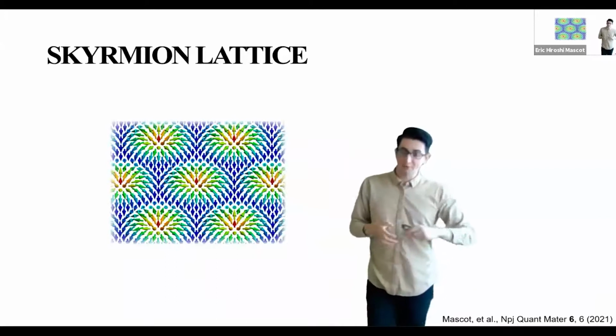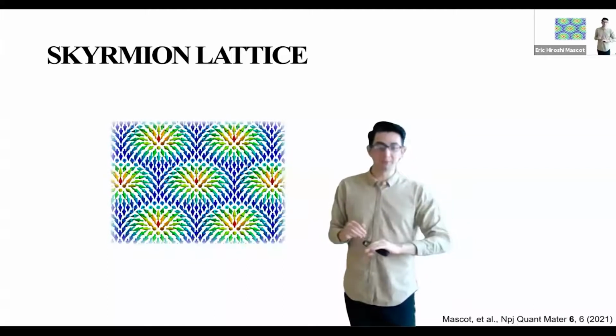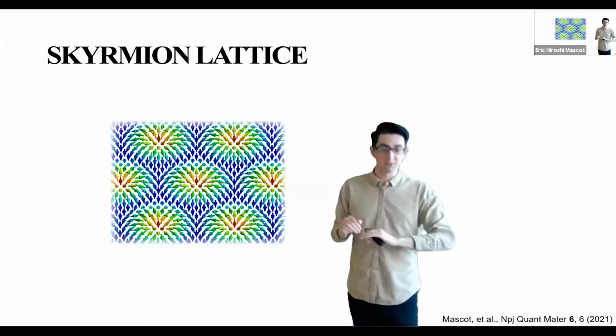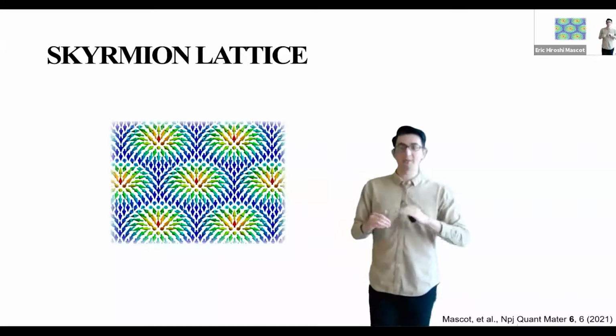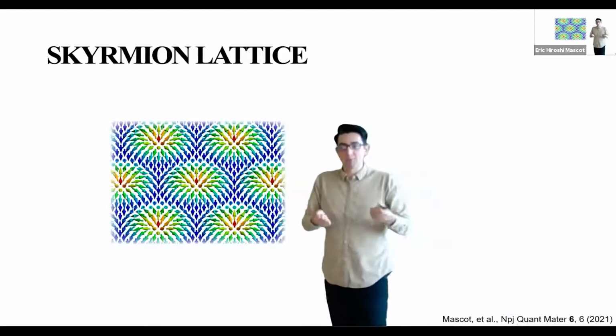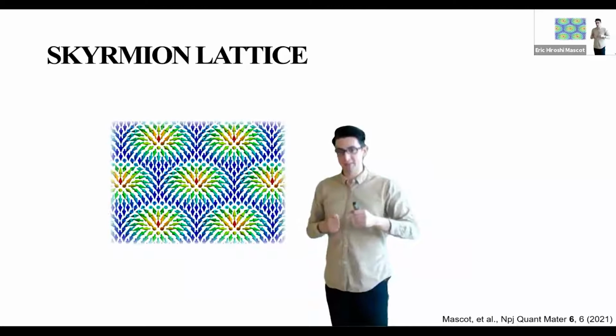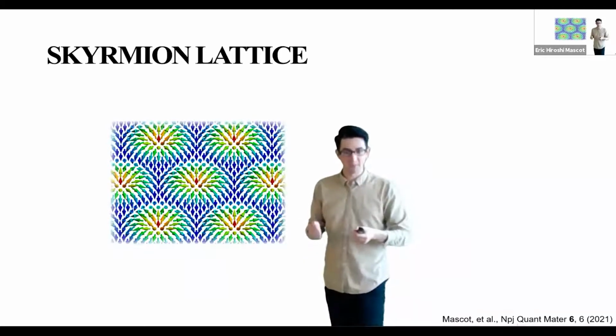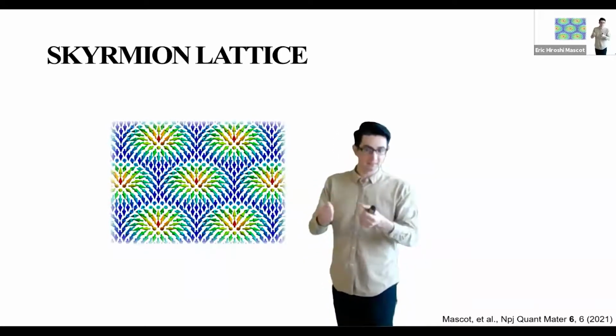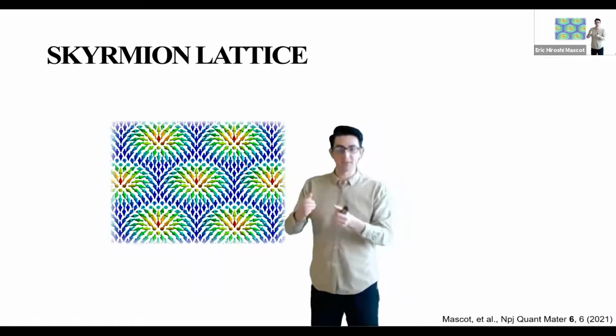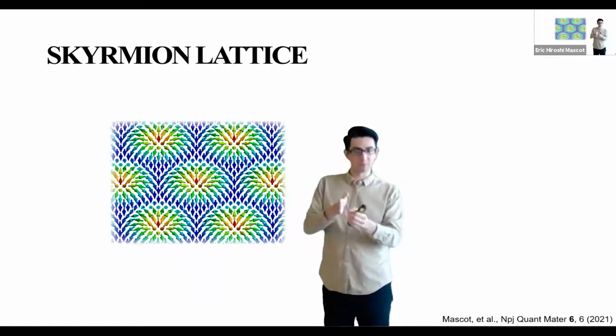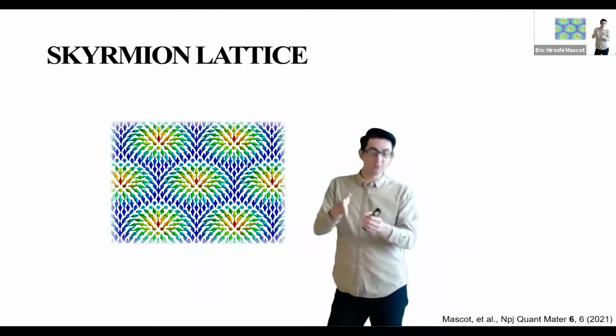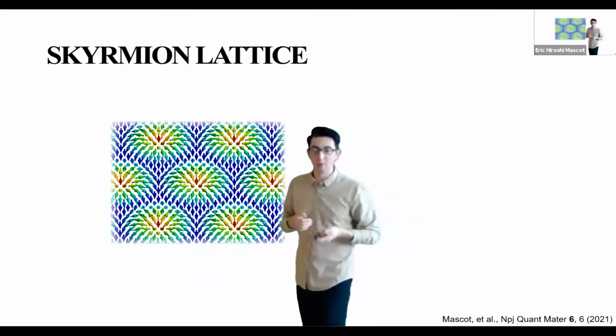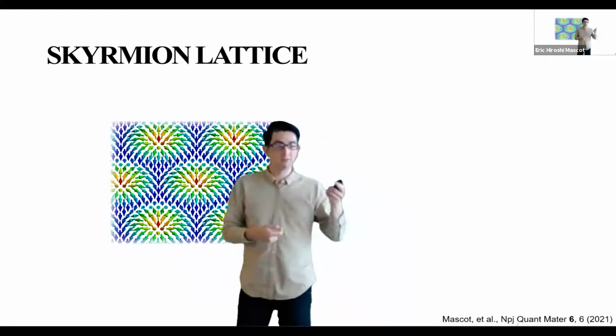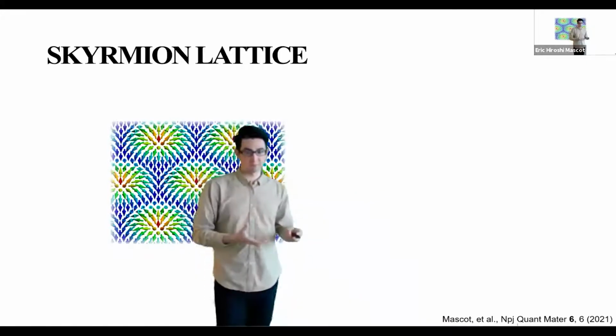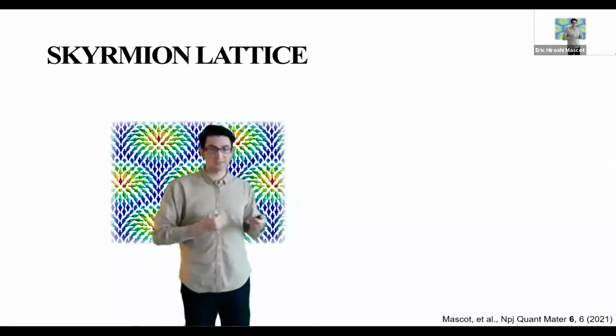And although there isn't a Rashba spin-orbit interaction in the superconducting substrate, what we can imagine doing is rotating each of these spins into a ferromagnetic ordering. But each site would rotate differently, and so the hopping between them would rotate as well. So if we look at how that hopping changes, we can induce an effective Rashba spin-orbit interaction. And so we can calculate that.